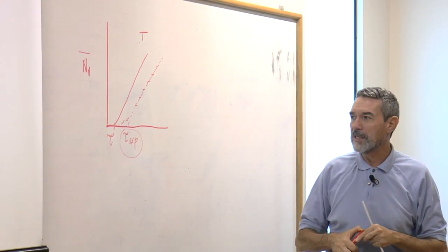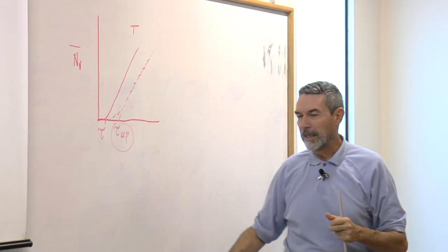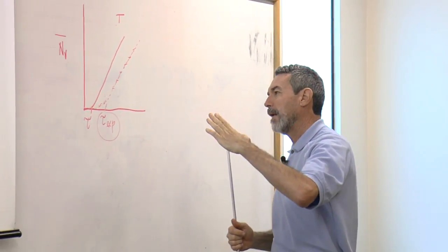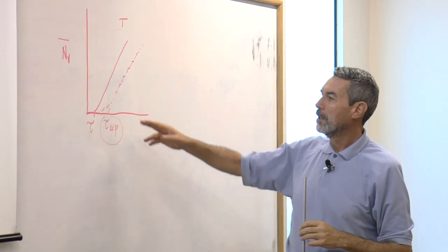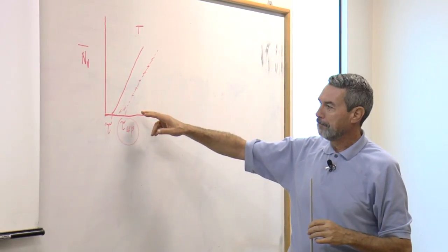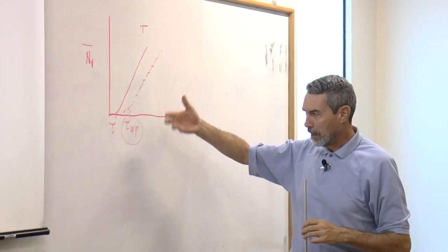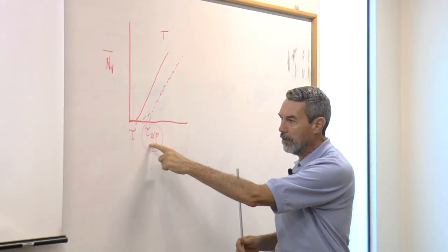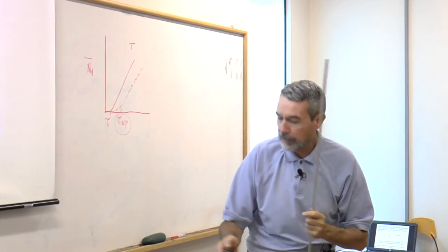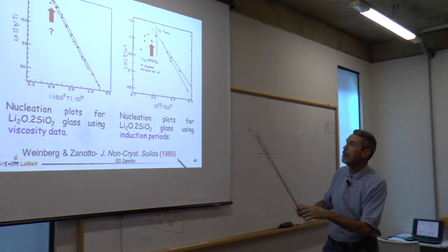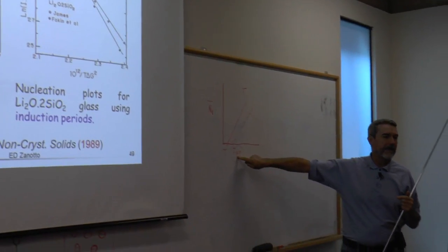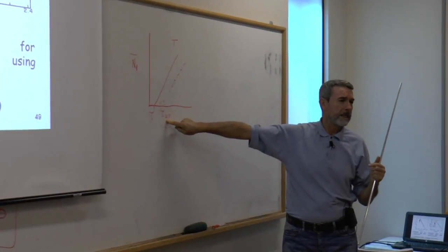It depends on the second heat treatment, on the development heat treatment temperature, and also on the heating rate that is used to heat treat the samples. So we have used the experimental taus in the analysis, and other people also did this.